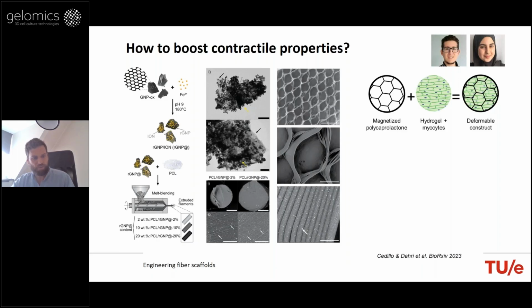And what we did then was to compound these particles with PCL using a melt blending approach that allowed us to fabricate extruded filaments. What you can see here from these images, the second column at the bottom, is the extruded blended PCL filaments, so polycaprolactone, with different concentrations of the iron oxide nanoparticles on top of reduced graphene oxide, and they were homogeneously distributed inside the PCL, which is typically a challenge when you create compounded materials with particles. By looking at melt blending, we could achieve so, and compound PCL with particle percentages up to 20%, which was quite good for us.